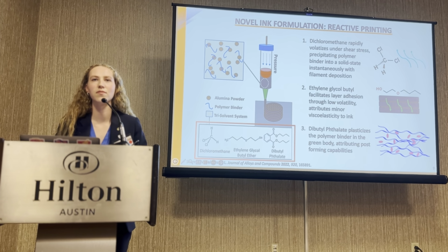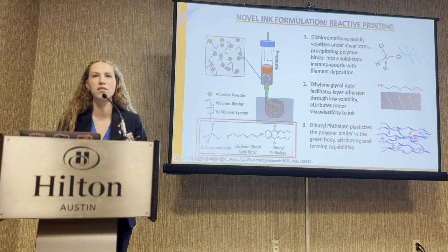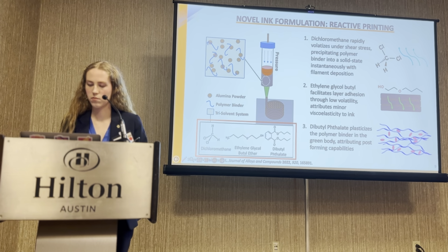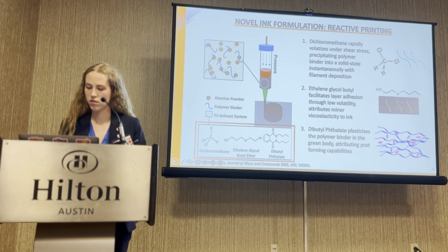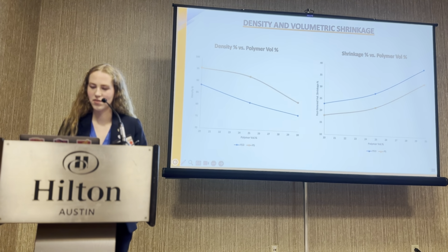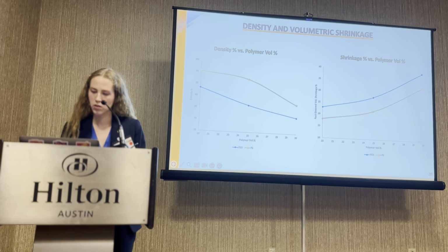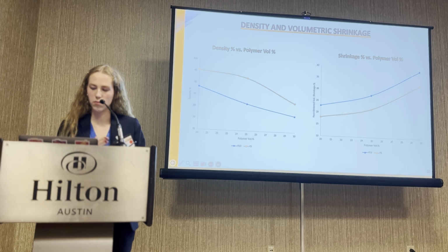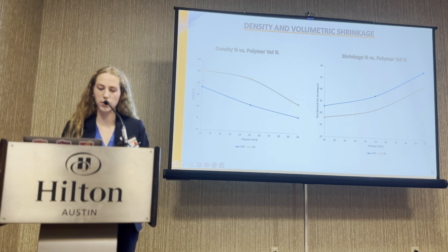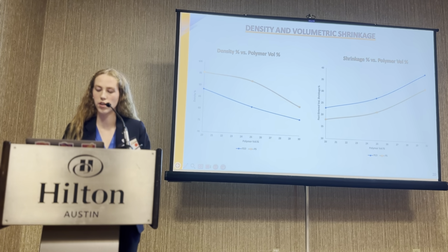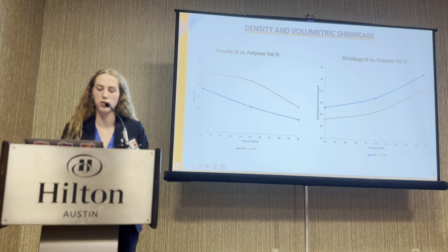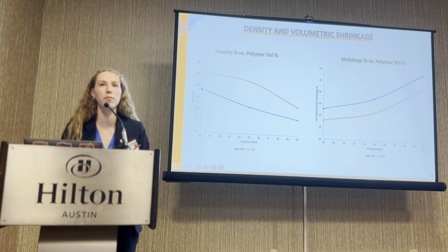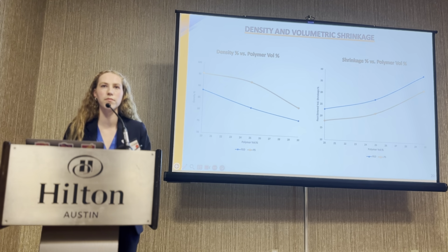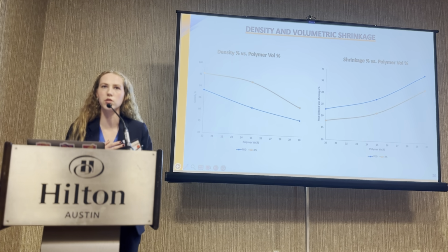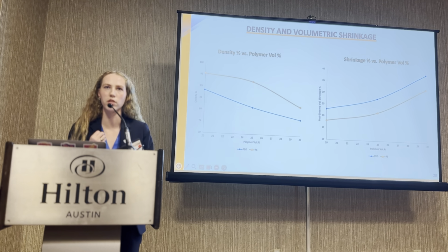I couldn't quite read from here. What was the shrinkage that you saw? So at the lowest polymer volume percent, it was around 17% for the polystyrene and around 23% for the PCL. Have you seen any cracking? No. Yeah, and that's partially due to that EGBE, which solidifies the shape.